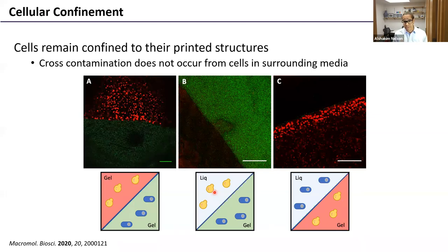But what we don't observe is the E. coli infiltrating into the yeast gel. And that's also true if we flip things around, if we have the green fluorescent E. coli in the liquid media and the red fluorescent yeast in the gel. So it appears that whatever cells or whatever microbe is inoculated into these gels, they seem to establish themselves in such a way that infiltration from the outside is not possible.